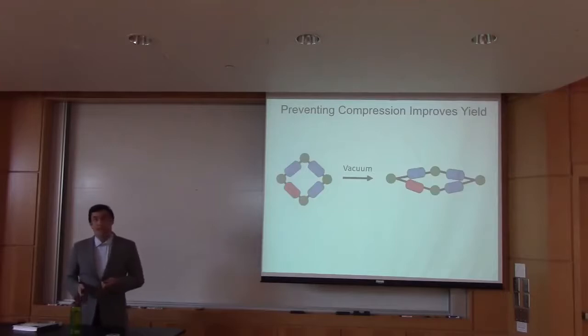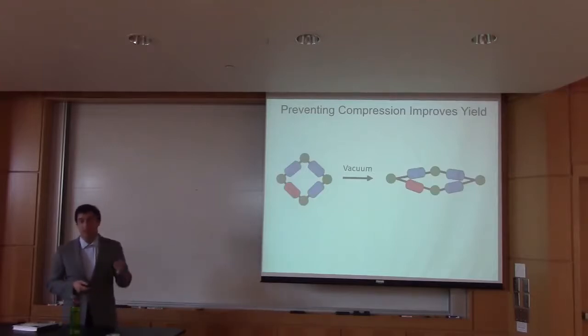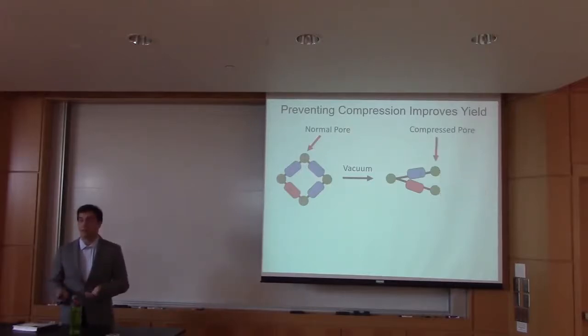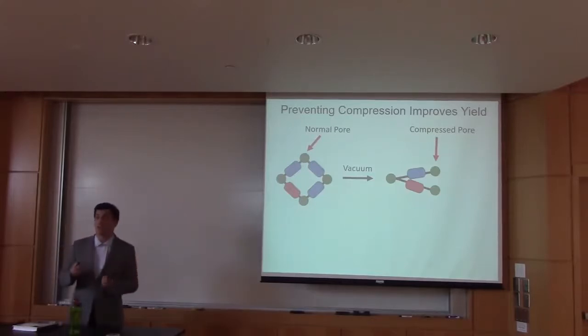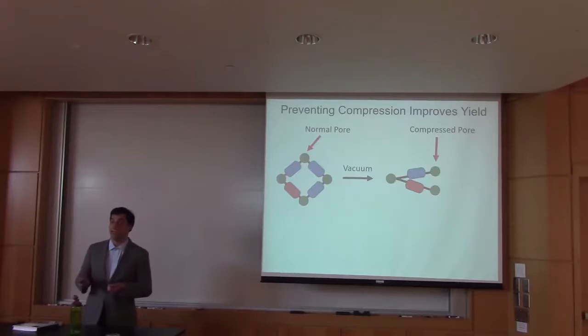What we think was happening is the same thing. We're now looking at a representation of a pore of the MOF I made. And once we pull vacuum, we don't have that reversibility. So we have our normal pore and our compressed pore. And after pulling vacuum for an extended period, we have that MOF decompose, and we're losing that structure and that rigidity. So once we're washing and adding that DMF, we're dissolving parts of our MOF and losing all of that product.